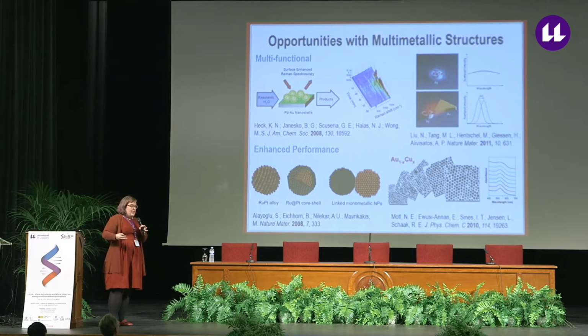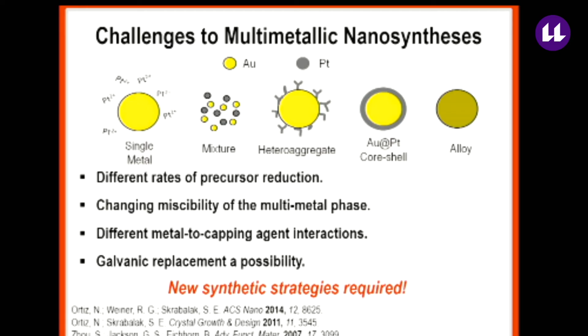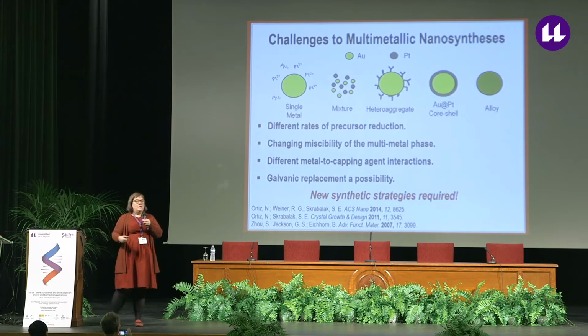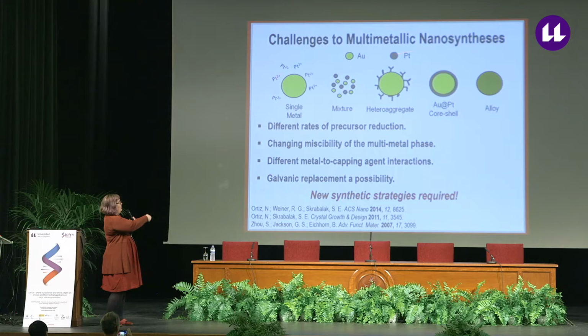But if you start to think about the synthesis of multi-metallic nanostructures, there's quite a bit of challenges that one may encounter that makes it incredibly challenging to have predictable outcomes in these types of nanomaterial syntheses. And the challenges arise because of our reliance on co-reduction techniques, where we're taking two or more metal precursors and trying to reduce or decompose those precursors to nucleate and then grow our multimetallic phase. In practice, those precursors are going to be reduced at different rates, which can give rise to a whole lot of different outcomes, as I highlight here in the case of gold and platinum.